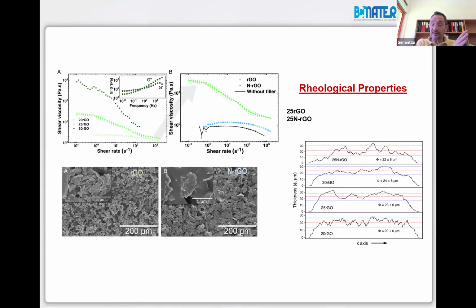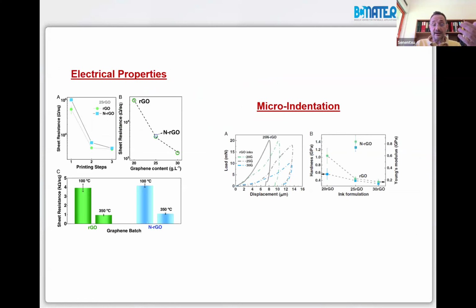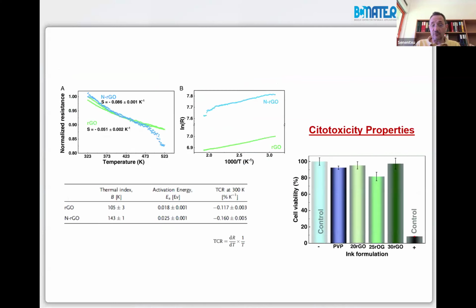Again, I can tune the sustainability by the filler, by the solvent, and by the polymer binder. No more elements are needed, but also I can tune the most important parameter for processing, that is rheology, one of the most important, and the functional characteristics just by the proper selection or functionalization of the filler. I do not need so many problems, and there I have a tuning of the sheet resistance, as I say, in more than an order of magnitude, and a tuning also of the adhesion to the surface I can print, again, only by using the specific formulation, okay?